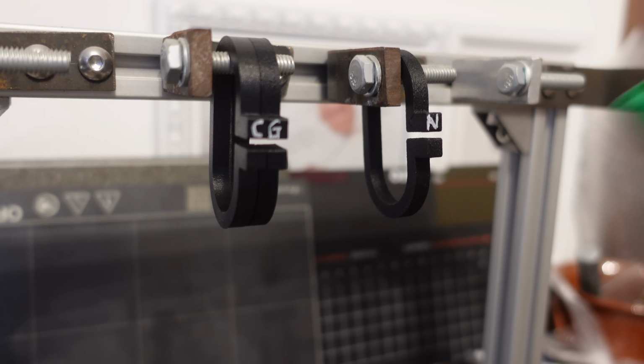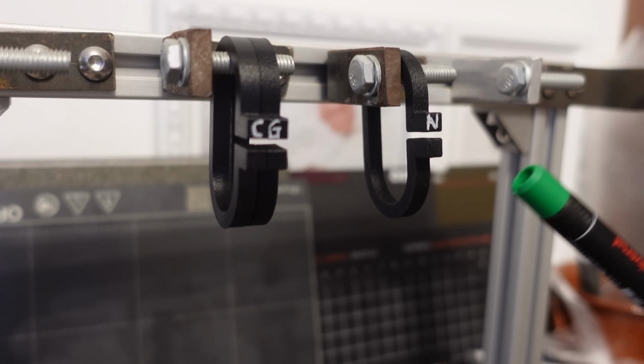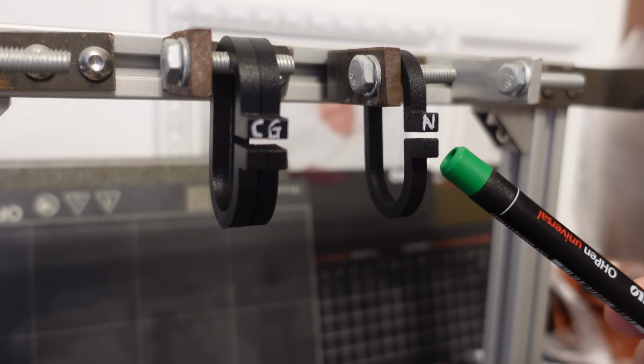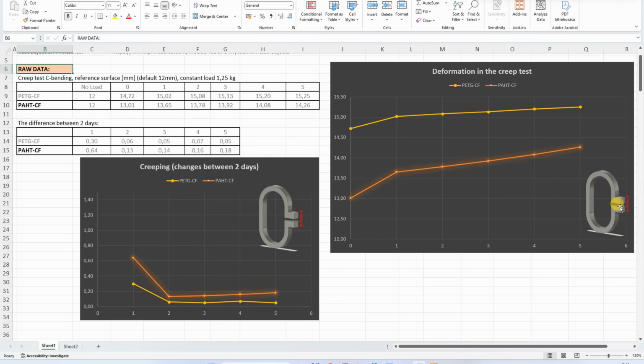Looks like it creeps and I don't really like this property, but after removing the load the permanent deformation is basically very minimal. On this graph we can see the distance between two reference surfaces, and we can see that the PAHT-CF has less deformation compared to the PETG-CF. But the creeping is the difference between 2 days. And on a second graph we can see that the PAHT-CF has more creeping compared to the PETG-CF. And this is typical for nylon, so don't be surprised. Annealing can help here a little bit, but overall I wouldn't place higher constant loads on nylons.